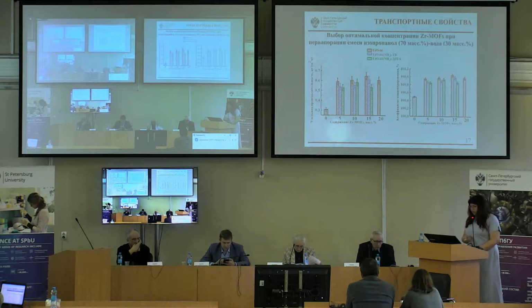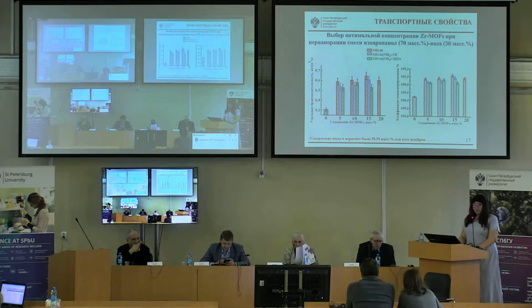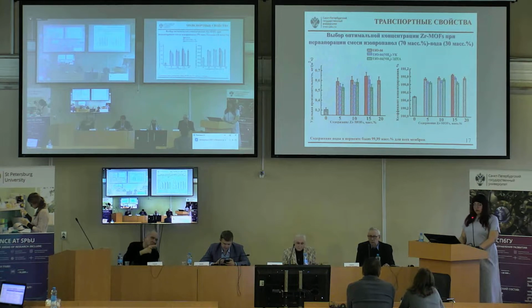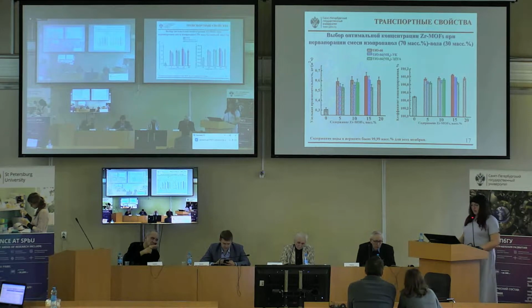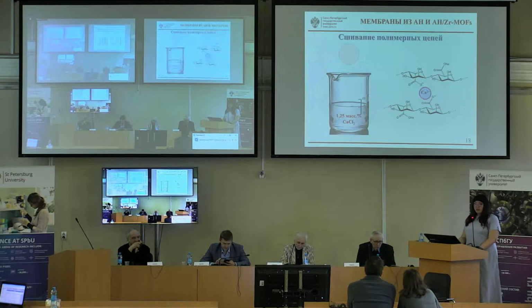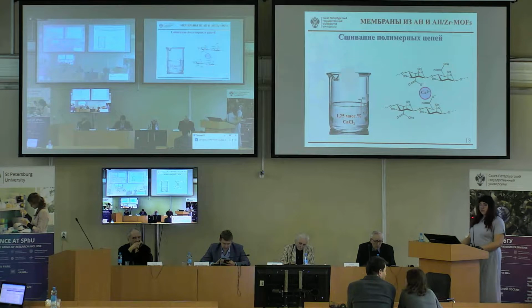The data presented in the histogram demonstrate that the introduction of MOFs into the sodium alginate matrix leads to an increase in the specific productivity and concentration factor while maintaining high membrane selectivity with respect to water. For the use of AN membranes in the separation of dilute solutions of isopropanol, their cross-linking is required.